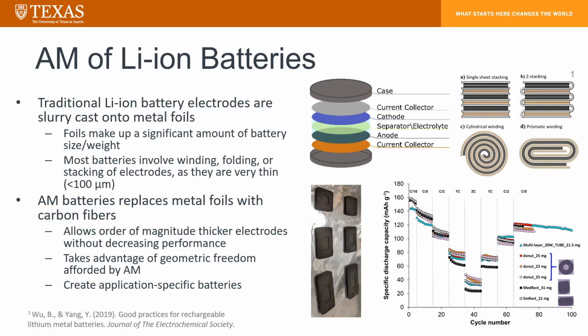Now, in your traditional lithium-ion battery, you have an anode and a cathode, collectively known as your electrodes, and they're quite thin. They're about 100 microns thick, or the thickness of a sheet of paper. So to give them structural integrity, they're mounted on some foils, so an aluminum foil or a copper foil. And to get the final battery cell, you would stack these with a separator between them, and then you wind it, fold it, or stack it to build up the large battery cells that you're familiar with. Now, the challenge is that those current collectors, those foils that we use there, take up a lot of space in that final battery, but they don't add anything to the actual capacity of the battery.